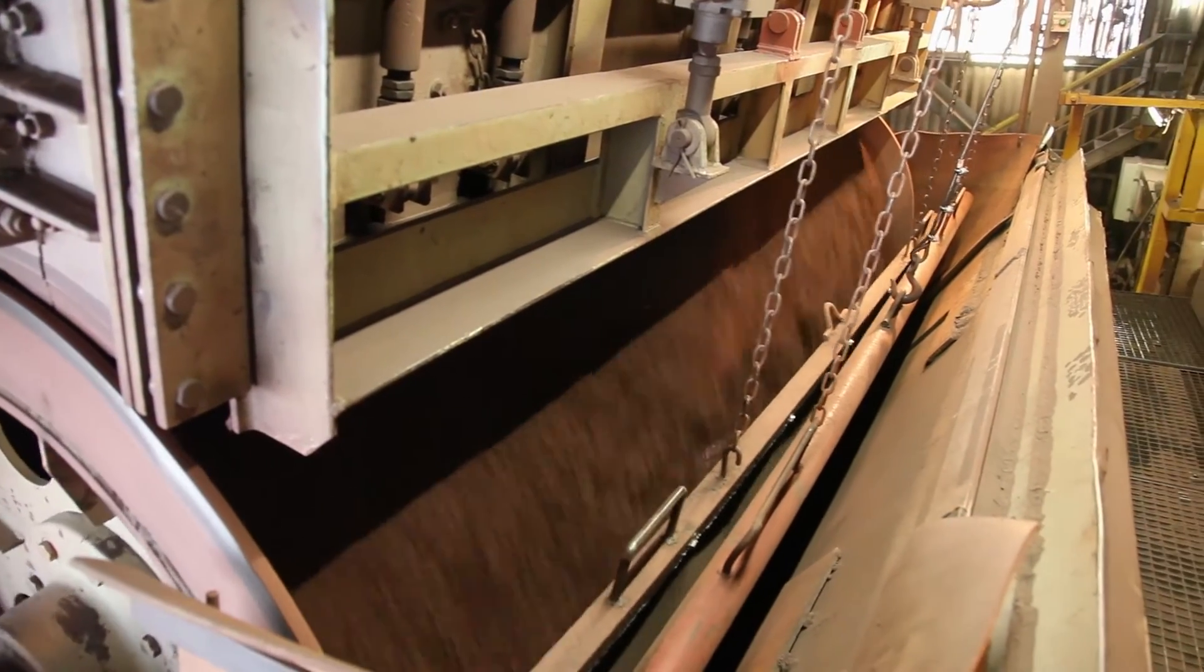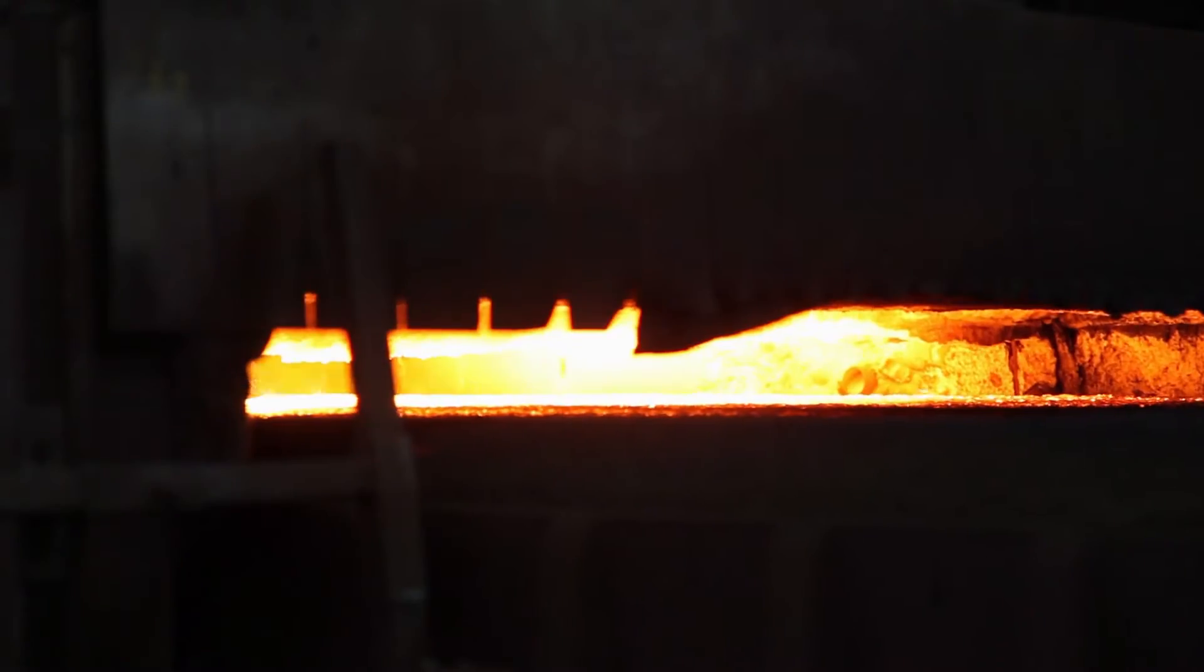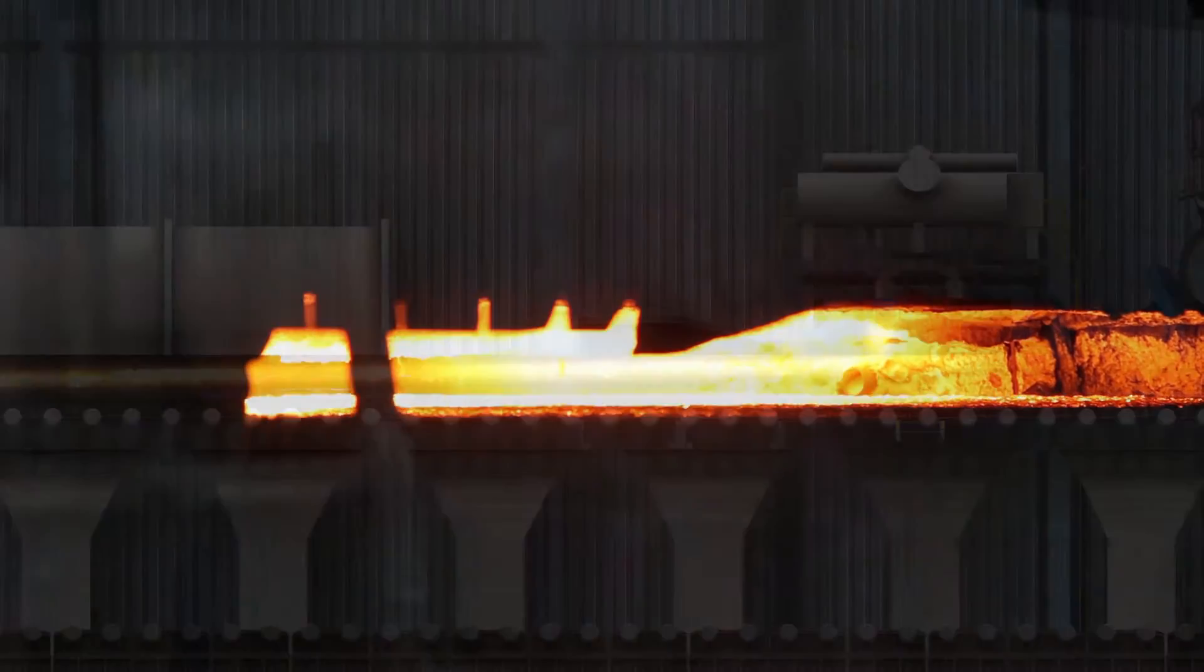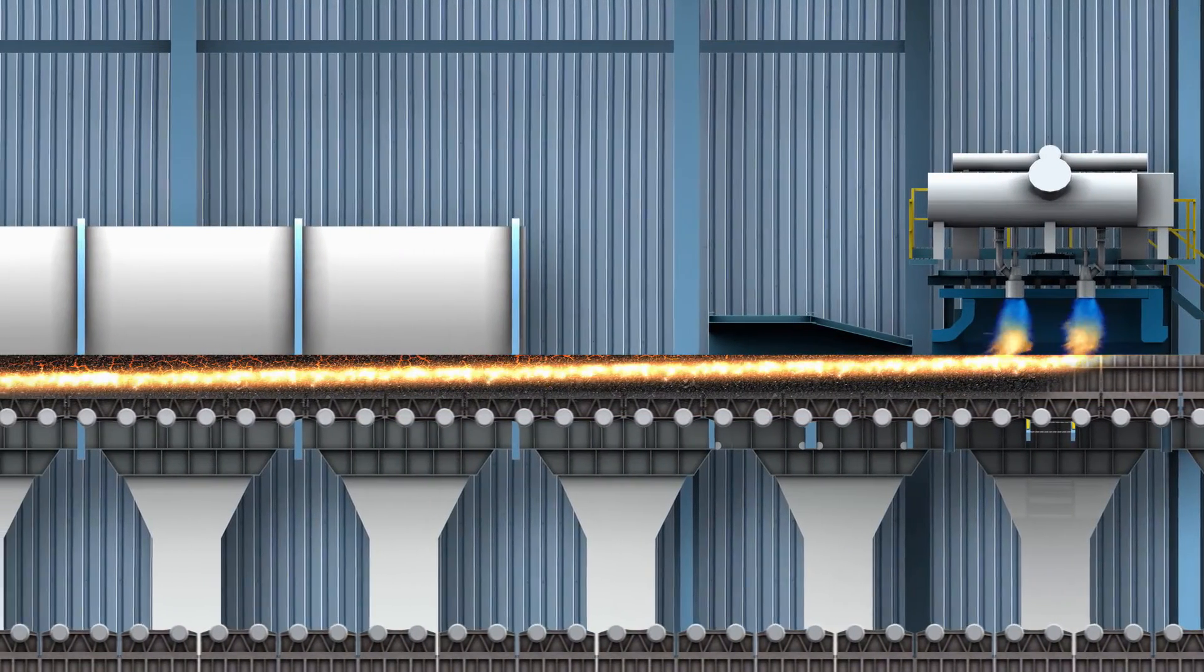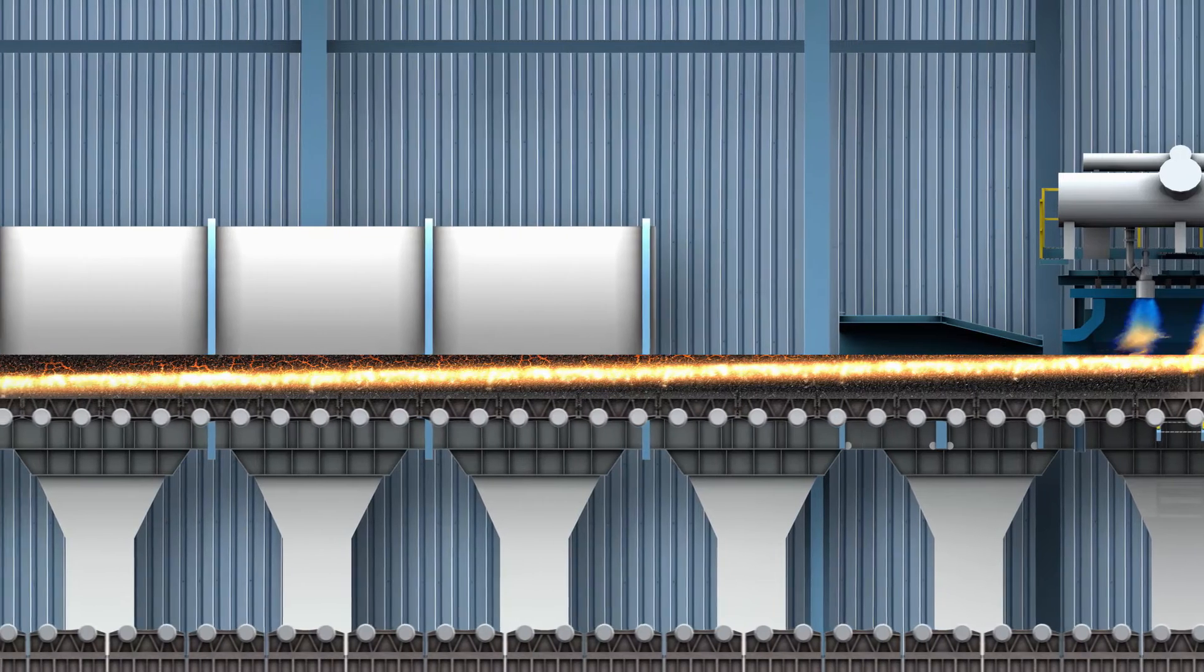The granulated material is then charged onto the sinter strand where it is ignited at between 1150 and 1250 degrees Celsius.